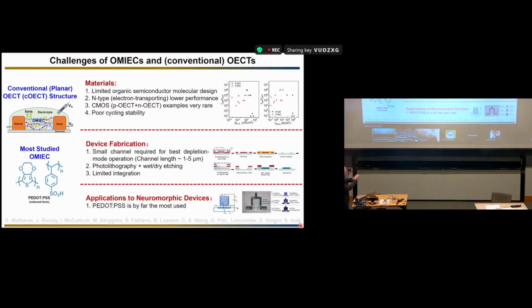And also, there is a problem with stability. When you turn this device on and off, you have a huge flux of ions going into the bulk and then coming out, going in, going out. So you can see that mechanically the semiconductor is stressed a lot, because it's not simply an electronic transport. Another issue is fabricating this device. Usually this separation is very small, on the order of a few microns, and this will require photolithography.